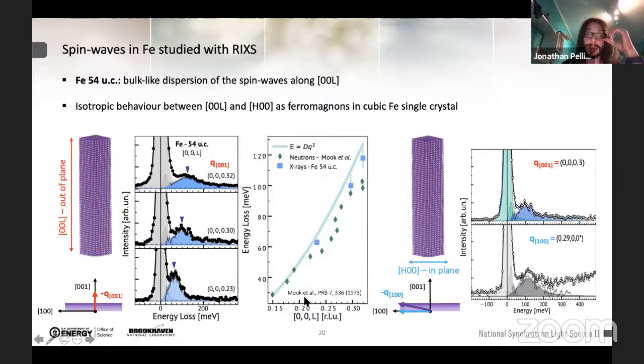And here on this plot, where I'm showing you the energy loss as a function of position along the 0,0,L direction, I'm showing you the comparison between our RIXS data and inelastic neutron scattering data that were collected back in the day. It is remarkable to see that our experimental measurements are pretty close to what was observed by inelastic neutron scattering. But as I said at the beginning, neutron scattering also observed an isotropy of the spin excitation along different crystallographic directions.